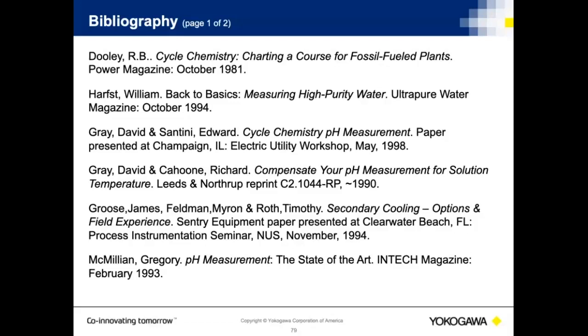And what was the test? The test is do the calculation for solution temperature compensation by measuring the pH at 2 different temperatures and see how great a value that is. If it's very minimal, then you can ignore it. If it's not, then you need to address it.